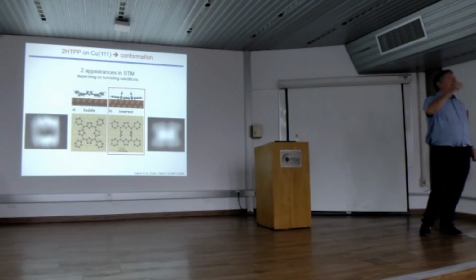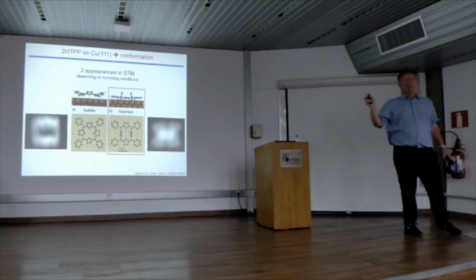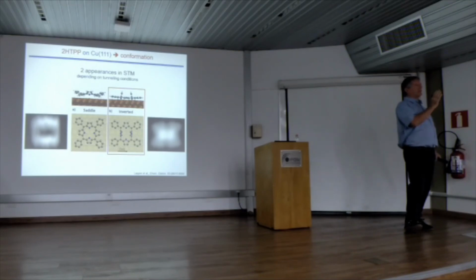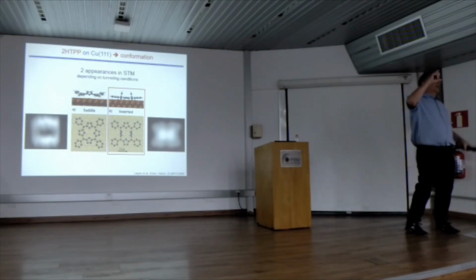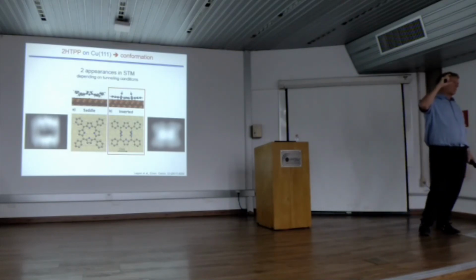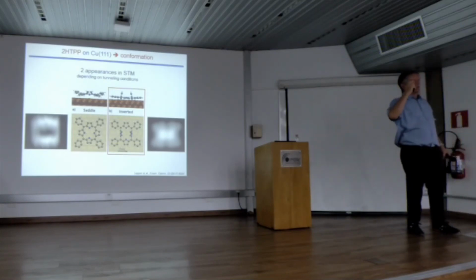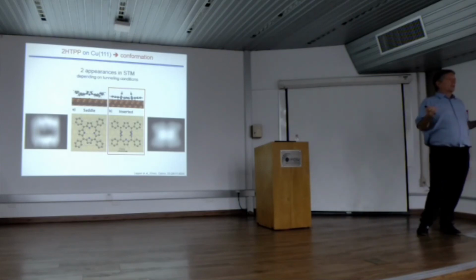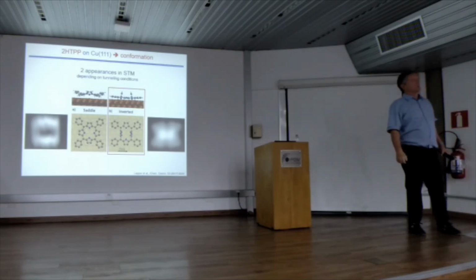So that means the appearance is stable over a relatively wide voltage range. So it's not like with the cobalt porphyrins, at 0.6 V, where there is an occupied state due to the interaction with the substrate. And if you go there, they are particularly bright. So we try to avoid that and work in a range where the appearance did not change with voltage. Also check with positive and negative voltages. Typically, you also always get images, and then you take the appearance which looks nicest. But all the effects I have shown you are independent of tip effects.